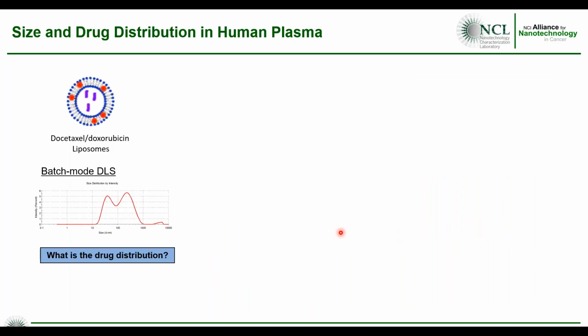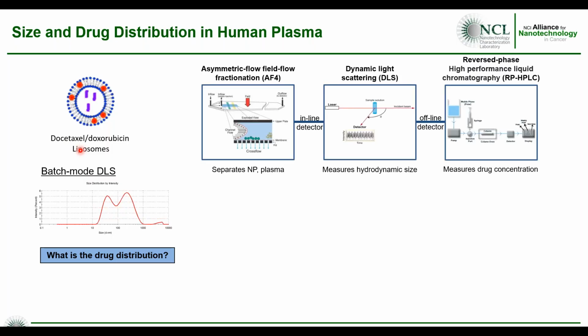We use a lot of AF4 to look at size and drug distribution in human plasma. So this is an example. We have docetaxel and doxorubicin loaded liposomes. If we do a batch mode DLS, we get a pretty polydispersed sample or size distribution. So this begs the question, where is the drug? You can pick any of these sizes, tell me what size has what drug and which drug, since there are 2 in this case. So we're using AF4 to separate out the nanoparticles with inline DLS, and then we're collecting fractions off of the AF4 and doing reverse phase HPLC for drug quantitation.